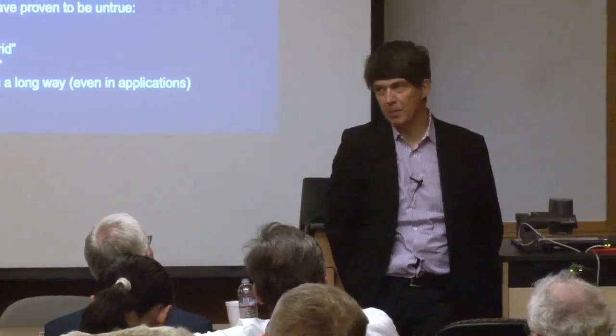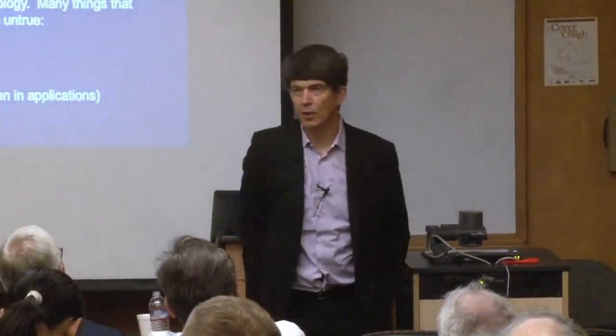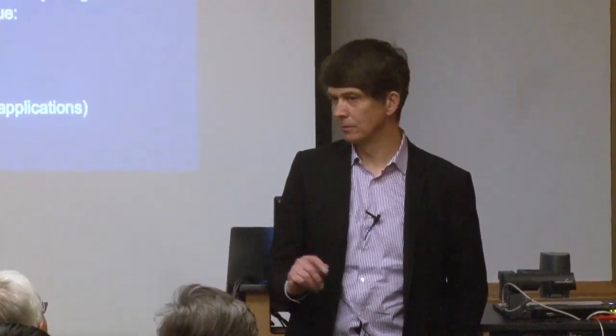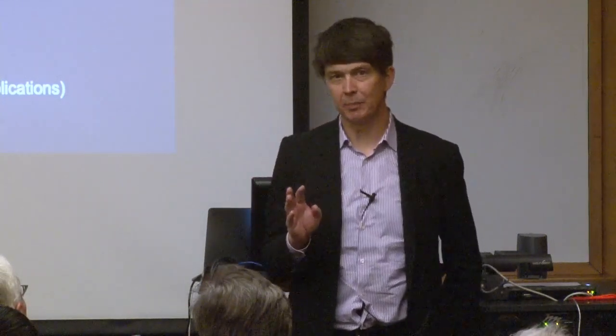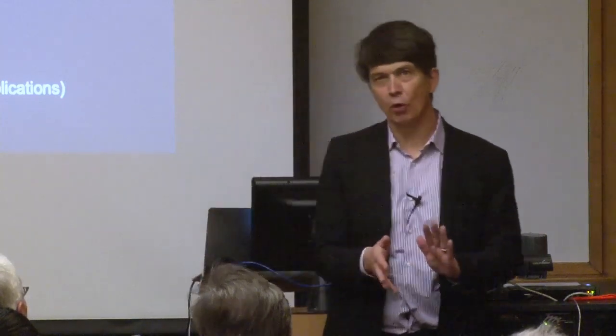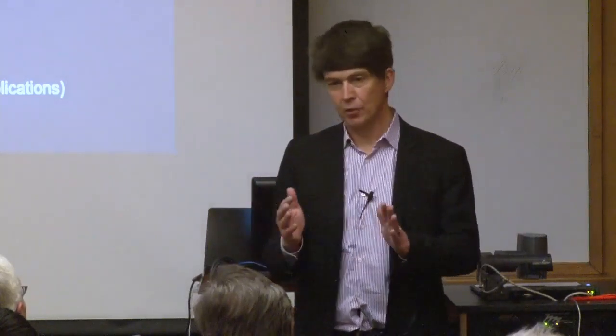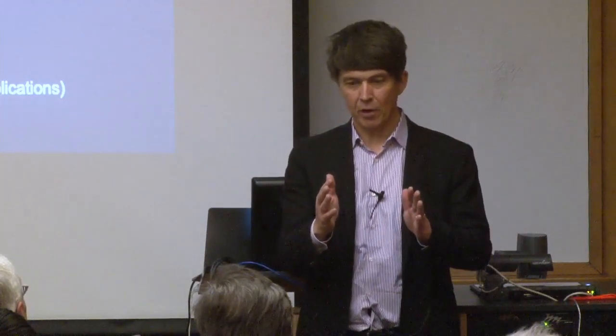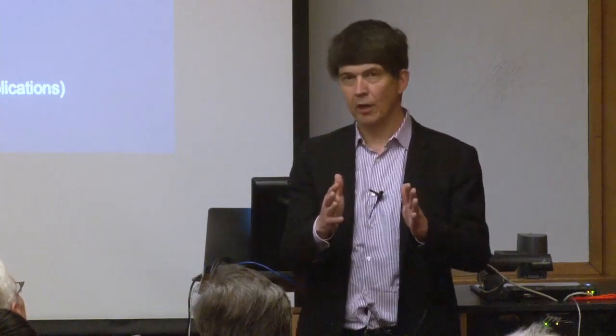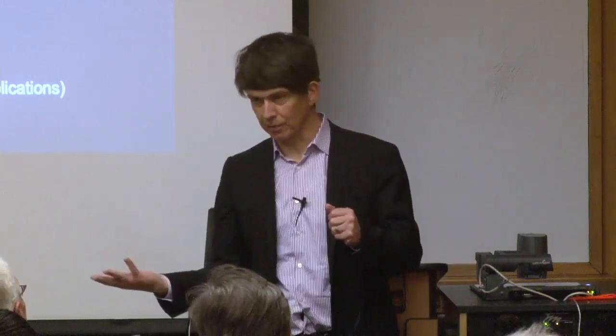So one issue you have to keep in mind that, so in batteries, the issue is largely about energy density, right? So you cannot give up volume. So while porous things look kind of appealing from transport perspective, from an energy density perspective, they're terrible, right? And the reason energy density is important, it's not just because my phone likes to be small, it's also because it drives cost. So if you have low density cathodes, you only get a certain amount of energy in a cell, and then you need to make more cells, and that kills you, right?